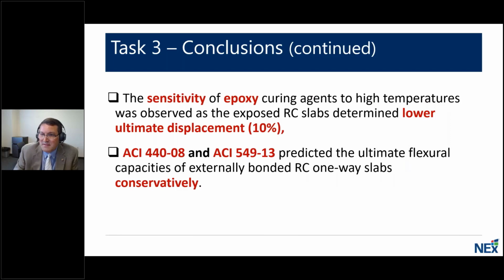And finally, the sensitivity of the epoxy curing agents to high temperature was observed, as the exposed reinforced concrete slabs showed a lower ultimate displacement, by 10%. And then we saw that the codes and standards were conservative, but on the SRP system a little bit less so.